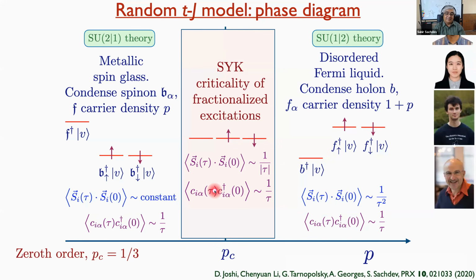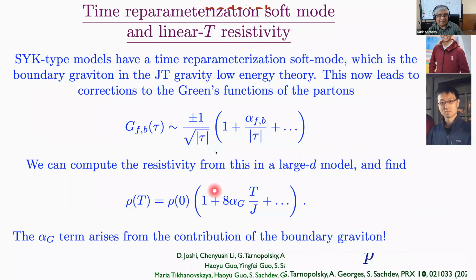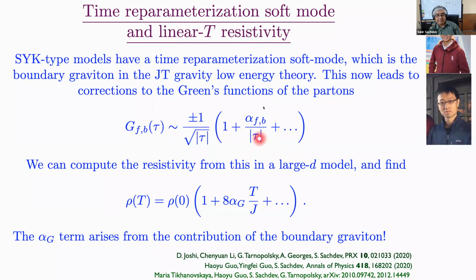Okay, and then you can ask, what are the corrections to the leading behavior? So these are very much SYK-like corrections. The leading correction to the Green's function is a 1 over tau correction. And this is intimately connected to this time reparameterization soft mode, which is the boundary graviton, JT gravity. So that's the correction. And now if you take this model in some finite large-M generalization, you compute the analog of the resistivity, you find indeed you get a linear T correction coming from this term, whereas the leading term gives you a constant down to 0 temperature.